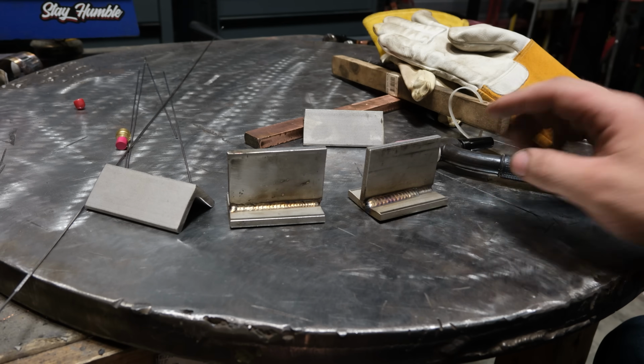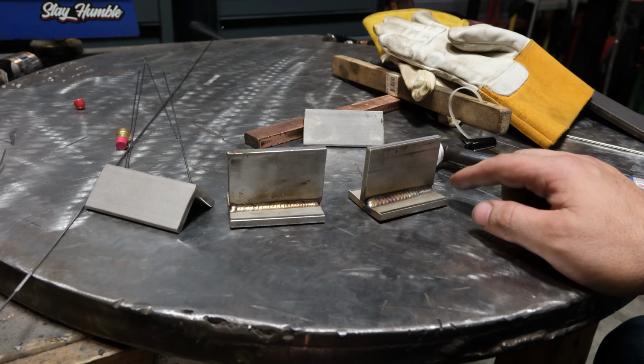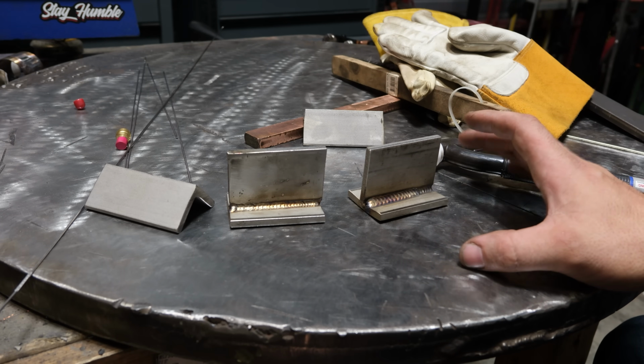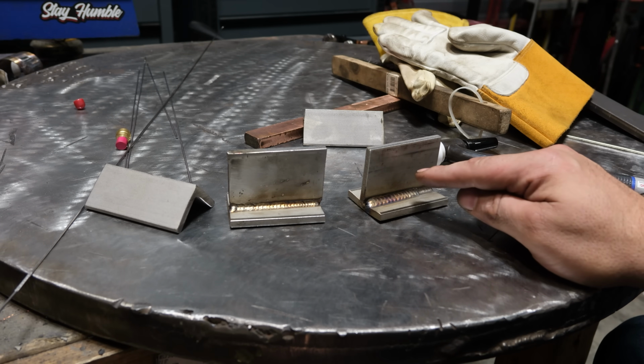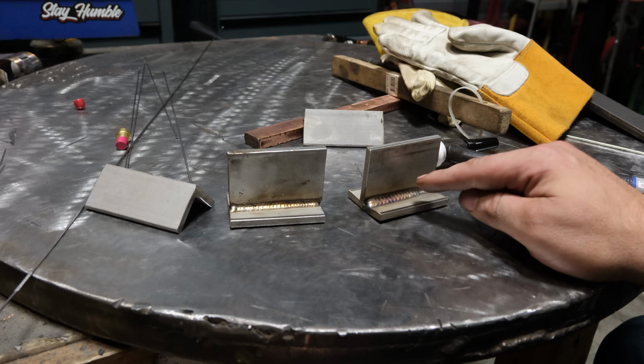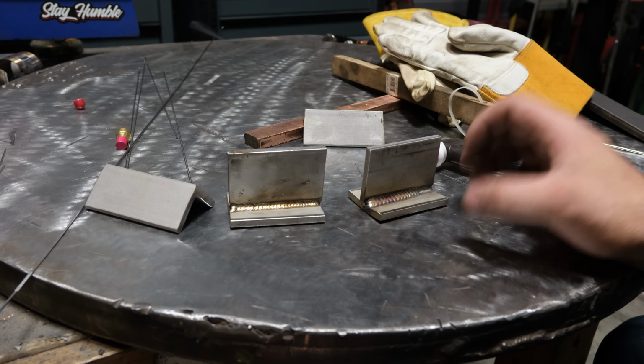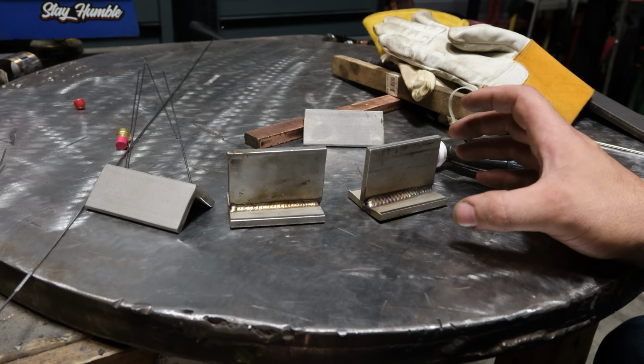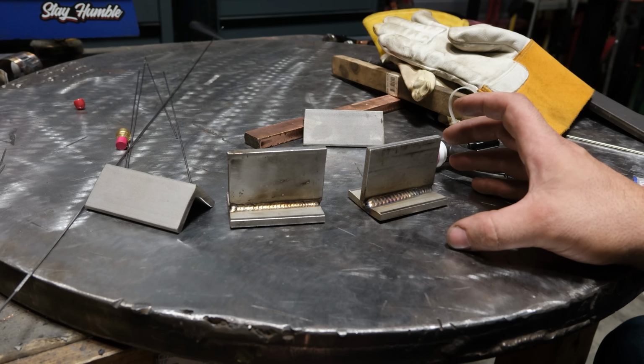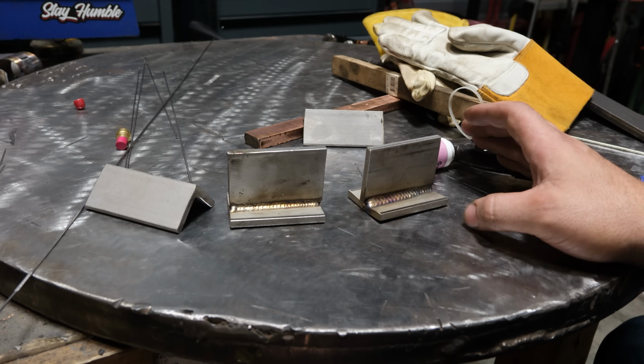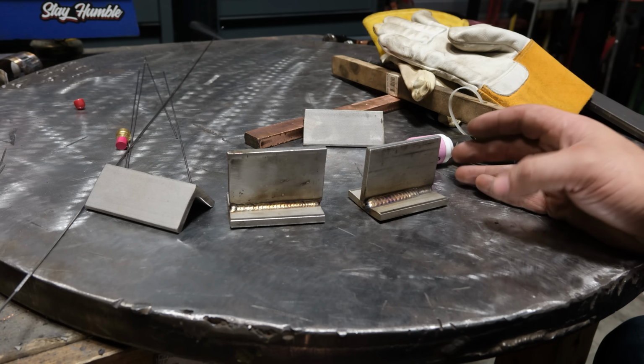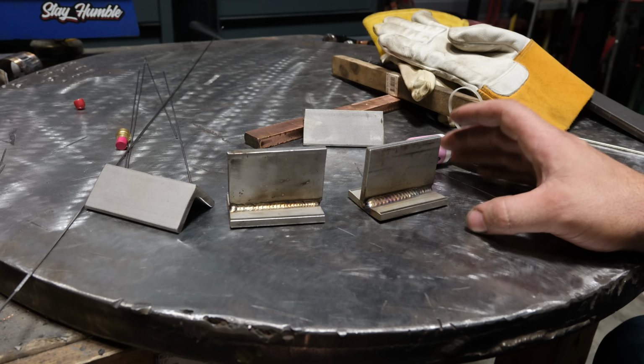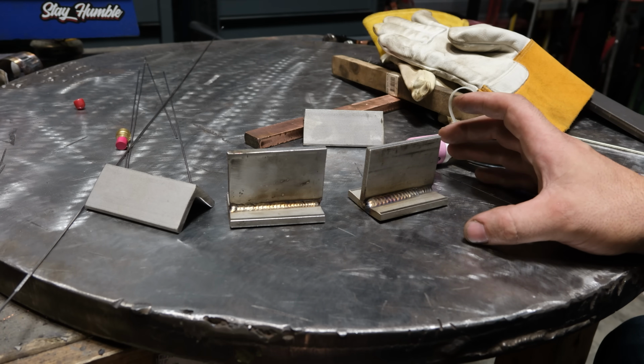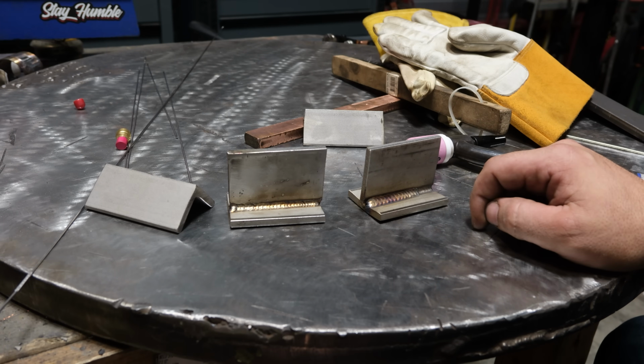despite the fact it's a small cup. Now the other main reason that this looks better than the thin sheet metal is simply because of the heat sink factor. These things have so much mass that it pulls the heat out of the weld, therefore you don't get the level of oxidization that you would find with thinner stuff. And that's why, like I said earlier, using the big cups and different tricks like chill blocks really matters a lot more with the thinner stuff than it does with this thicker stuff.